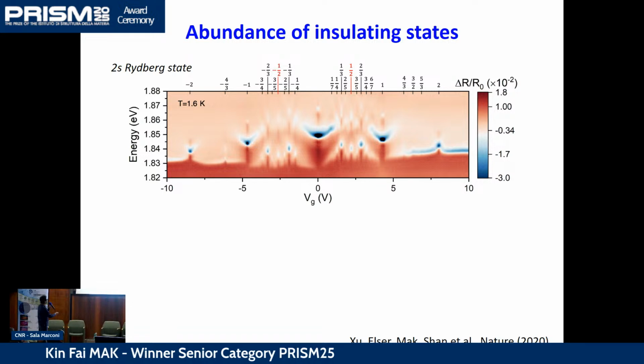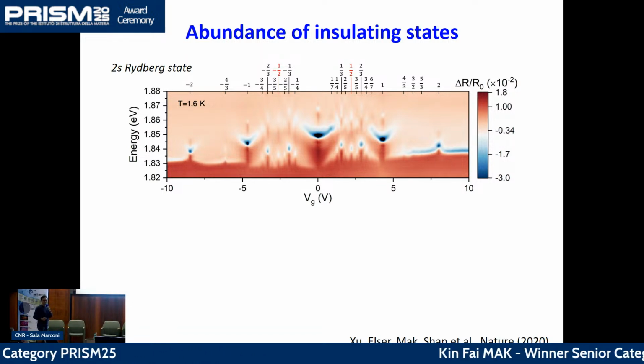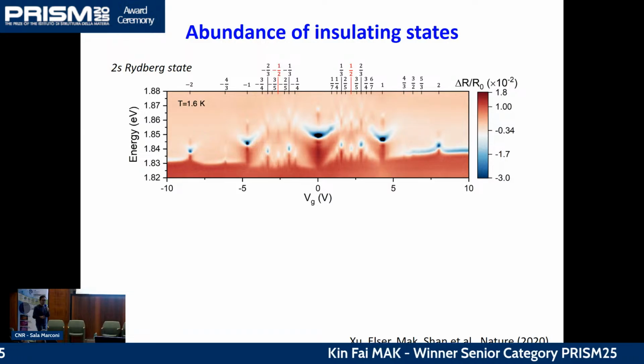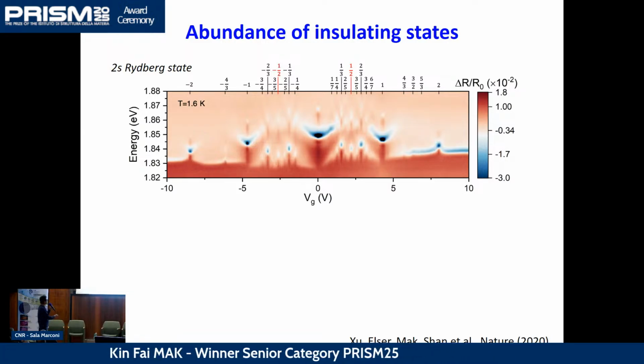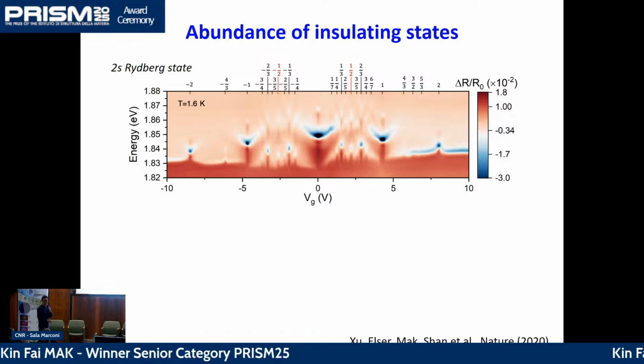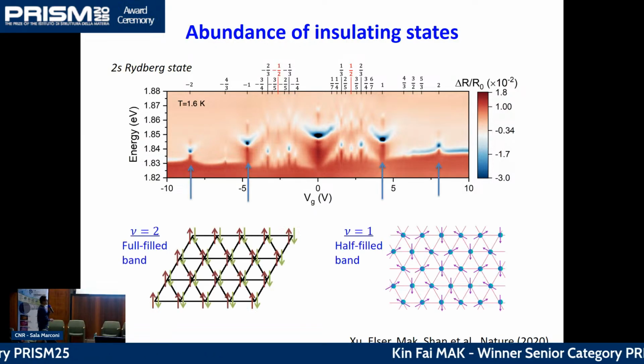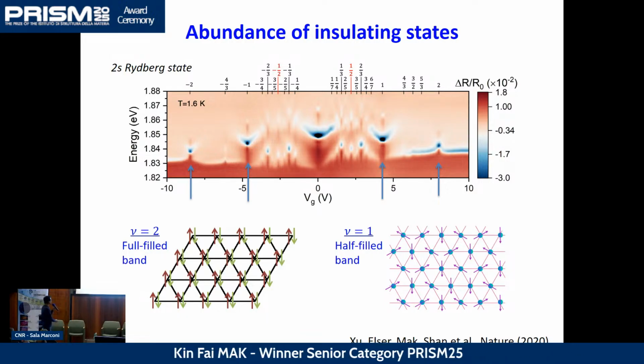And every time you see a bright spot here with a blue shift in energy, that means a stronger excitonic effect and a larger exciton binding energy. That means each of these bright peaks corresponds to an insulating state. The background corresponds to metallic states. Okay. So let's take a look at the simpler example of these states.